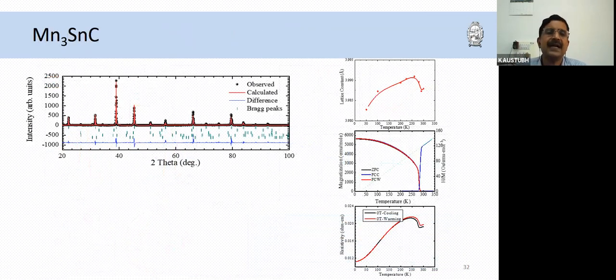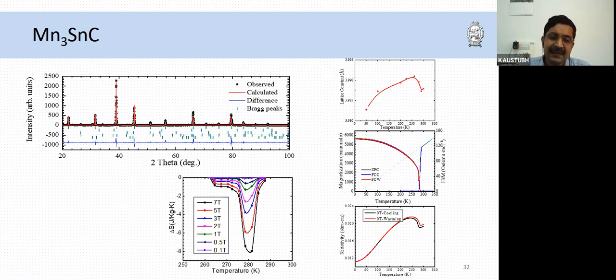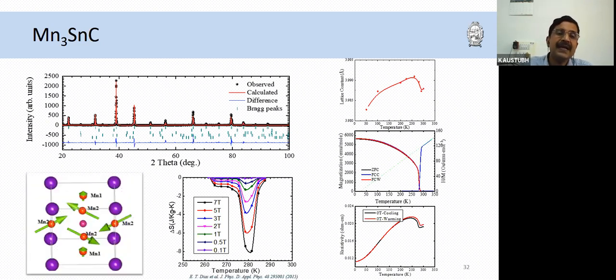So with this knowledge, we tried to look at manganese tin carbon, Mn3SnC, which is also cubic at room temperature, and it also shows a first order transition, the same type of volume expansion transition at the magnetic transition. But in this case, the magnetization, when recorded, was typical of a ferro or ferrimagnet. Even the paramagnetic Curie temperature was positive, indicating that there are ferromagnetic correlations. And the entropy change was very high and very close to room temperature, which is a good thing. But when we did neutron diffraction, we could see both orders, the antiferromagnetic order along the 110 direction, as I said, and the ferromagnetic order.